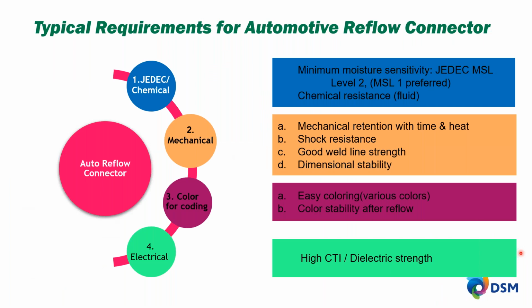So what kind of requirements are there on the plastics that are used on reflow connectors? The first one we talk about is JEDEC or chemical resistance performance. JEDEC is a way of rating how prone the material is to blistering as it sees the heat of the reflow process. And we'll talk about that in a minute. JEDEC MSL, for moisture sensitivity level, the lowest rating is MSL level 1, which is the highest or best rating. In mechanical performance, the material has to withstand, keep its mechanical properties even under the heat of the reflow process. So you can't have significant melting or deformation.